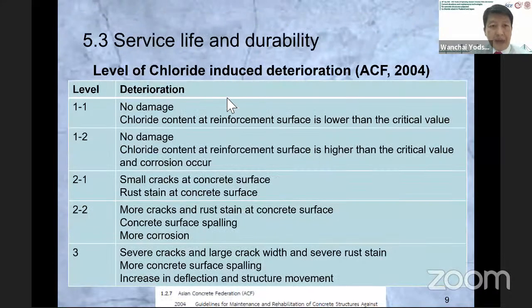And for the service life and durability, we have a level of chloride-induced deterioration. For this level of deterioration, we have a reference from the Asian Concrete Federation. We have levels 1-1, 1-2, 2-1, 2-2, and 3. Level 1-1 means the deterioration is no damage and the chloride content at reinforcement surface is lower than the critical value. And for example, in case of level 3, we have severe cracks, large crack width, severe rust stain, more concrete surface spalling, and increase in deflection and structure movement. This one is part 5.3.